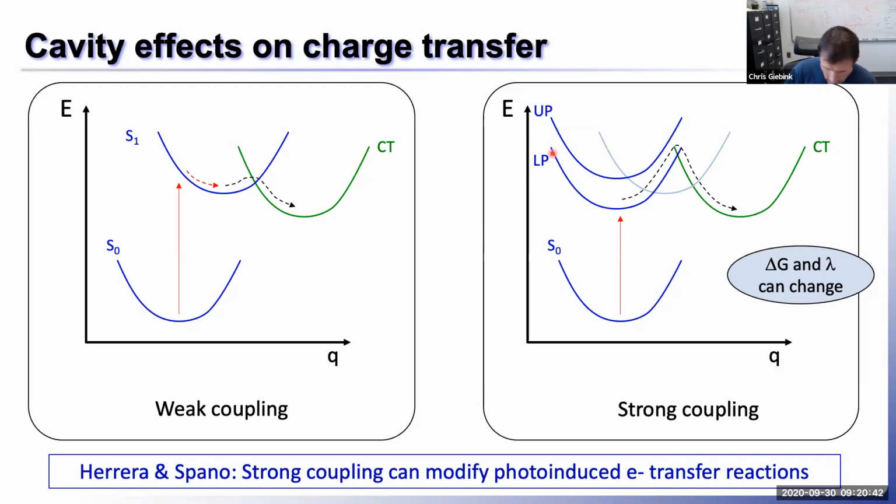You can look at this from a couple different perspectives. At some level, the fact that you've delocalized a single excitation over a lot of different molecules means that you're essentially inheriting most of the ground state from all these different molecules. But from a classical phenomenological picture, you can also look at it from a dynamic standpoint. When you've got a very high Rabi flapping rate, the excitation is essentially transferring on and off molecules faster than their nuclei can actually reorganize.